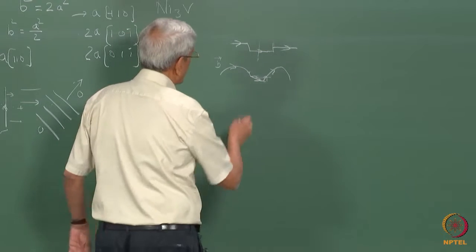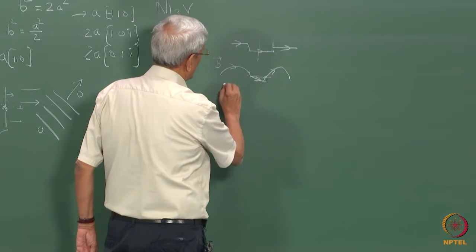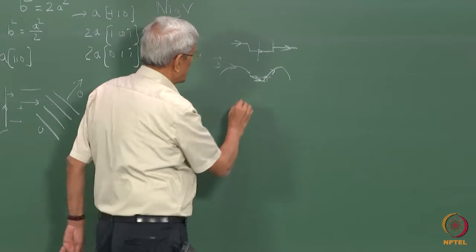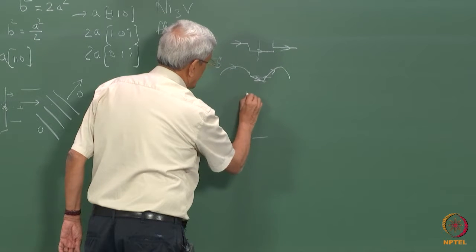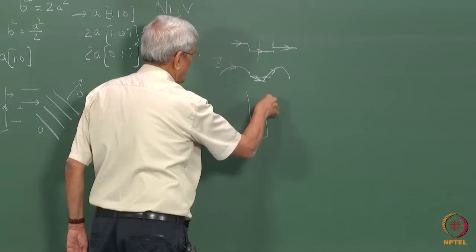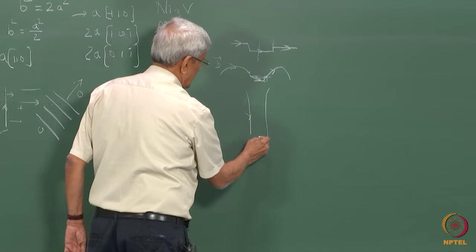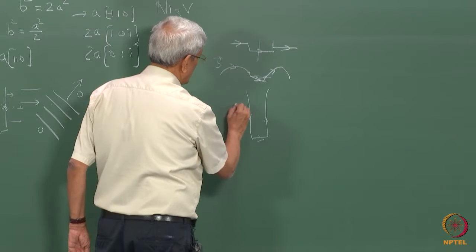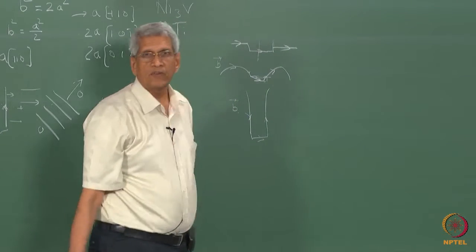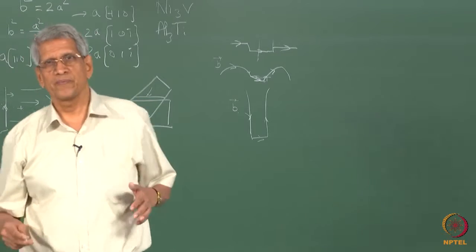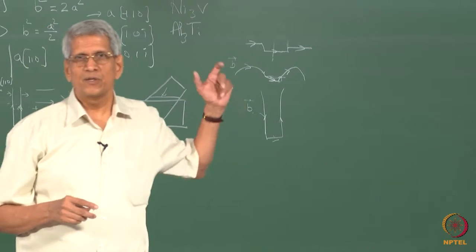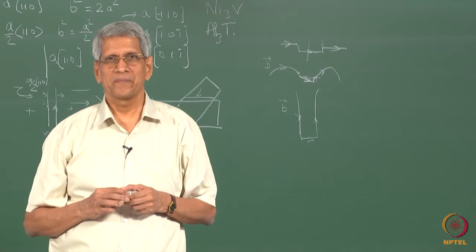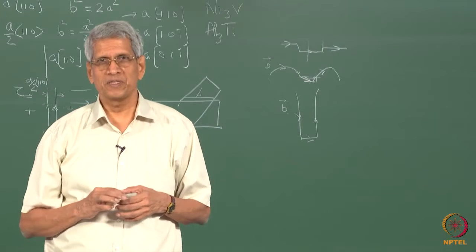So under the action of the stress, what can happen is that this can move quite high. This is stuck in this region. So we will have one region that has come like this, another region has gone up like this. This is how dislocations with the same Burgers vector and different line senses, we call it a dipole. So this sort of reaction can happen where dipoles can be created. This is one possible reaction.